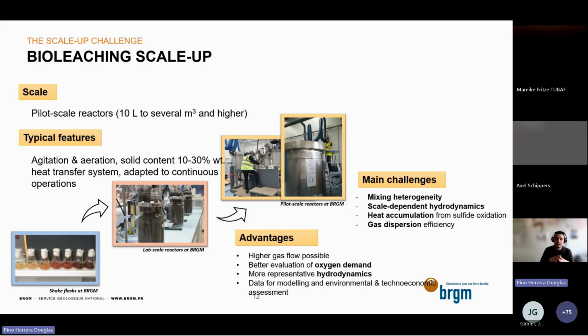So what we generally do is, once we study the system and know that efficient leaching is done in small reactors, we go to pilot scale reactors, from 10 liters to several cubic meters and more. And then we can go to 10 to 30% solids, which is the real scale solid content in the pulp. These systems are more adapted to continuous operations. It's possible to obtain higher gas flows, but we need to be careful that the transfer in the system is still efficient enough. So we have a better evaluation of the oxygen demand and more representative dynamics of the system.